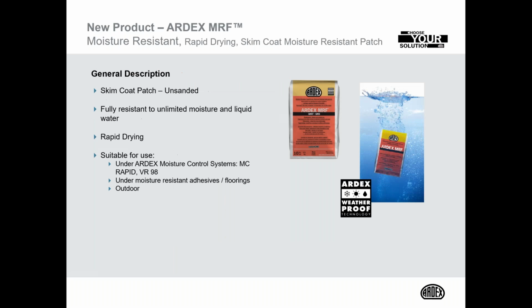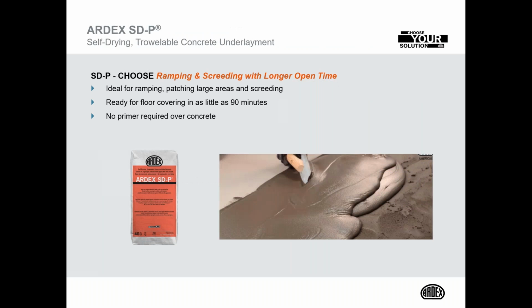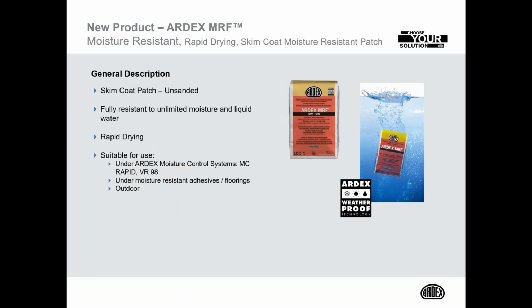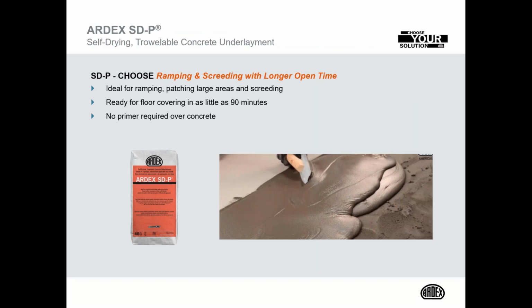SDP is a sanded material, has sand in it, and it's designed for ramping and screeding and floating applications, 1 inch thick, 2 inches, 3 inches thick. So you can make transitions with this, create ramps with this material, but it's self-drying, so it's like a rock in about an hour. You can put floor covering on it in as little as 60 to 90 minutes. So SDP is your rampable, slopable, screedable type transitioning repair mortar. Feather finish is your unsanded skim coat product. Both products are self-drying and allow flooring on them in as little as 60 to 90 minutes.